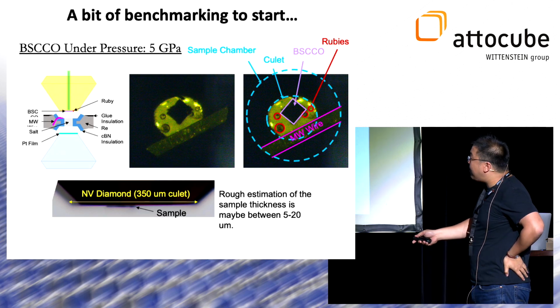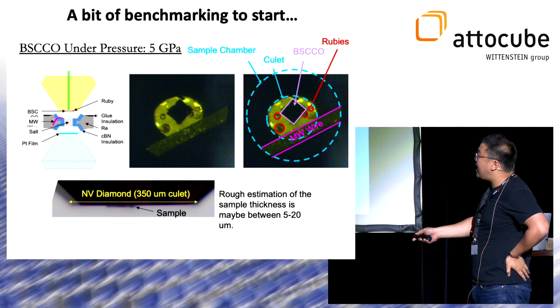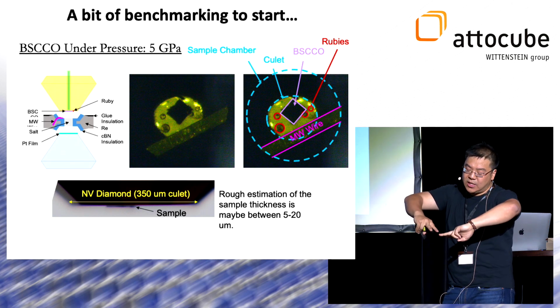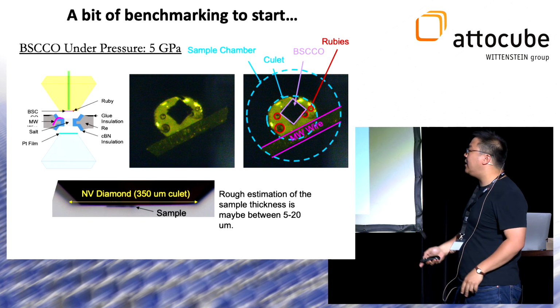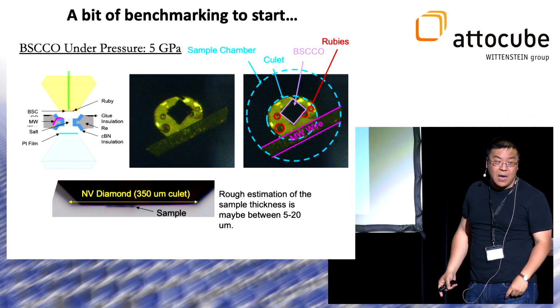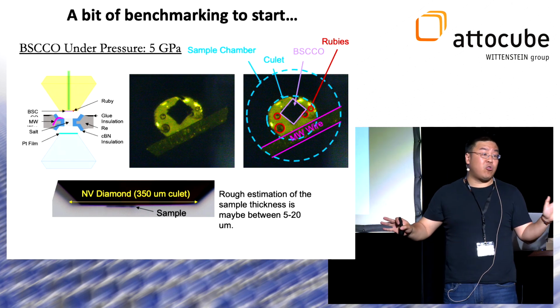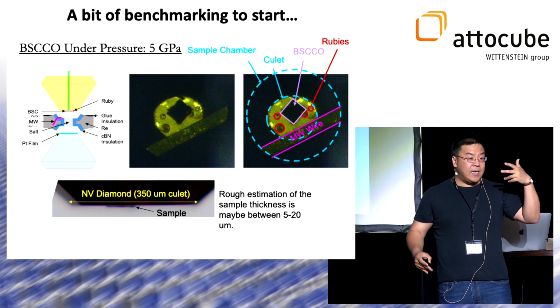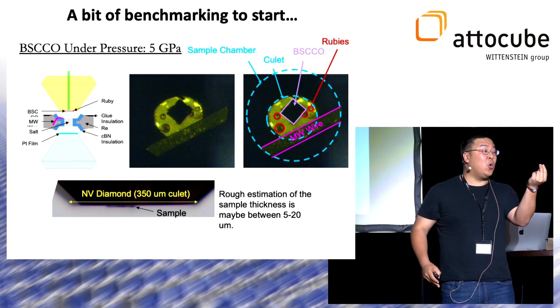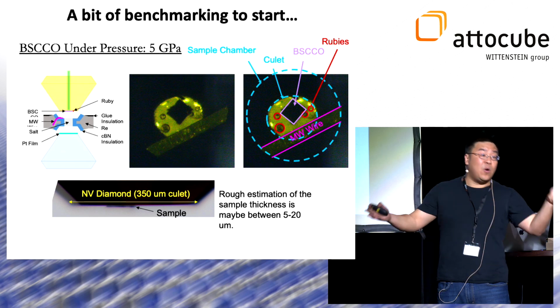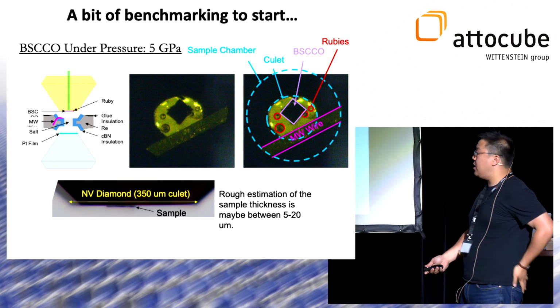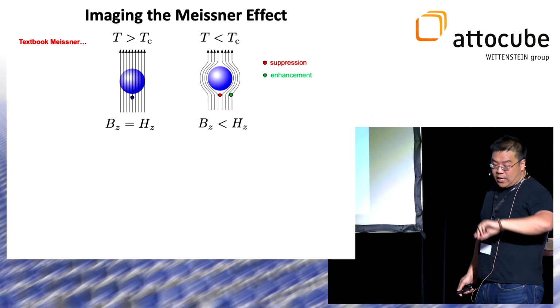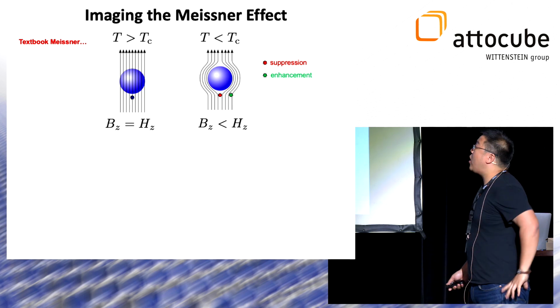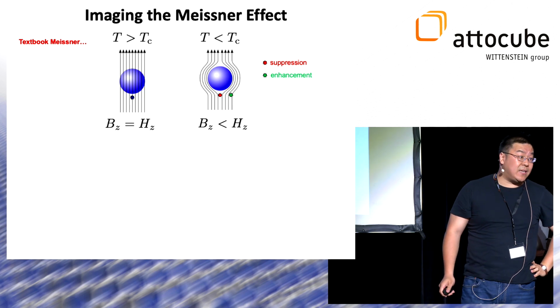You can see that the sample is stuck on top of the diamond anvil. We apply leads to this by pushing the sample into the leads to be able to do transport at the same time. The basic set of measurements that my group does on all of these systems is a combination of transport and local magnetic field imaging. I'll focus on the magnetism because that's the thing that's new. So just a very quick reminder about what one should expect in the system.